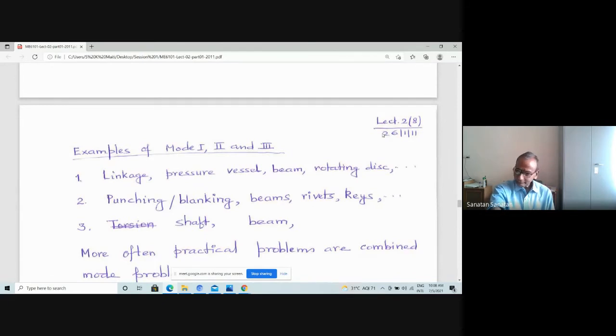So let us get a little bit comfortable about what these modes are, where they occur, and why we should bother about them. You see examples of mode 1, mode 2, mode 3. Particularly mode 1: think of any linkage mechanism. By the side of the railway track, you will find that some links are there, and they push as the carriage goes, and when they are pulled and pushed, they are subjected to loading in the axial direction. Similarly, think of a pressure vessel under internal pressure, and if you have a crack in the axial direction in the material, that is also subjected to opening mode. Beam, if the beam is subjected to loading, let's say a cantilever beam, and you have a crack perpendicular to the axial direction, that is also subjected to opening mode.